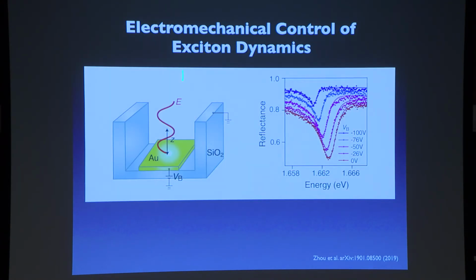So when you shine the laser light onto the gold mirror, what you're generating is these standing wave-like patterns of electric field. And then what we are doing is moving those atomically thin semiconductors through those standing wave-like patterns. Sometimes those excitons see the maximum electric field, and as a consequence, they will reflect a lot.